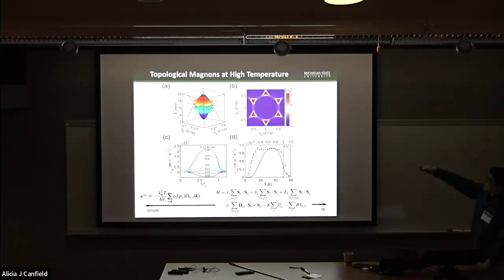So naturally, without the DM interaction, we can see that the magnon bands cross each other. But if we take into account the DM interaction, then the magnon bands will open a gap at a K point. So around this gap opening point, we see a very large Berry curvature. And such a large Berry curvature is going to give rise to large thermal conductivity.